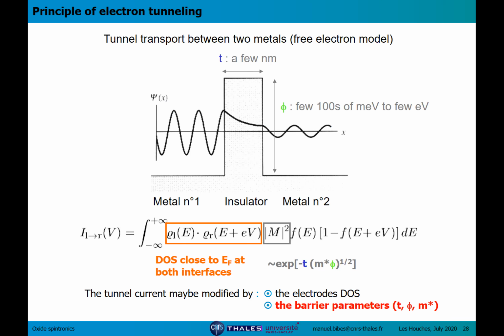But if we come back to this slide I've shown you, we see that in addition to the density of states, which, as I hope I've convinced you, is very important in determining the physics of tunneling, especially in spin-dependent tunneling, we have these tunneling matrix elements, through which the tunneling current is going to depend exponentially on the barrier parameters. So if one could find a way to act on the barrier parameters, the barrier height, the barrier thickness, or the tunneling effective mass, which is somehow related to the decay rates of the wave functions that I was showing you for NGO, if one could act on that with external stimuli, magnetic field, electric field, then potentially you could reach very strong variation of the tunneling currents because of this exponential dependence.